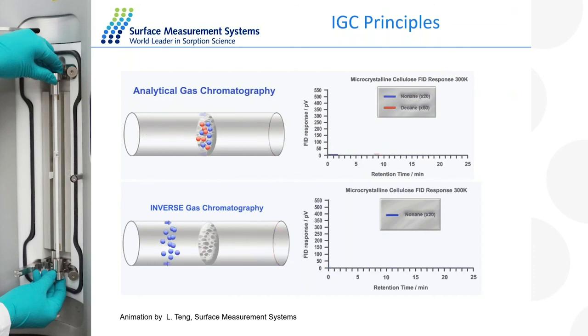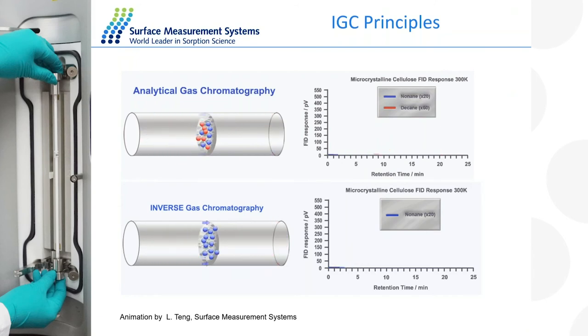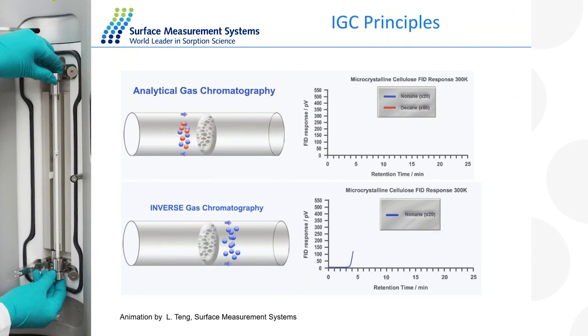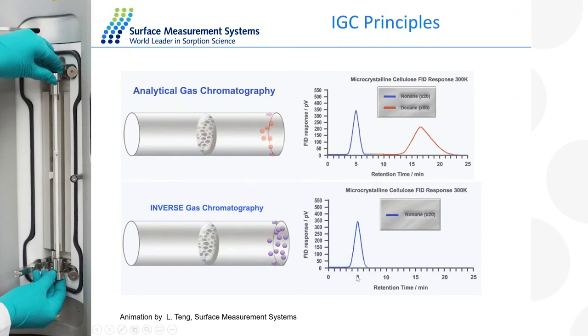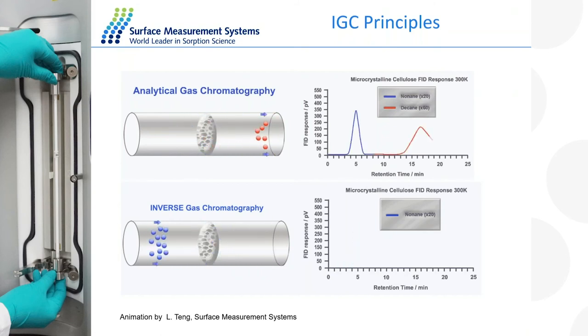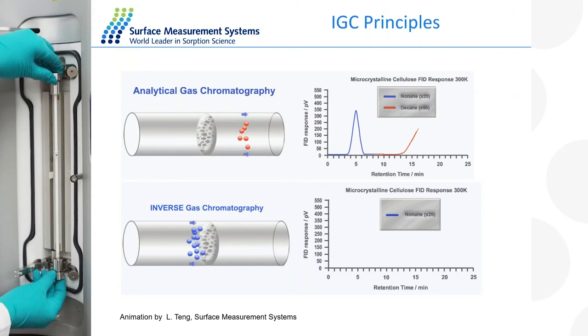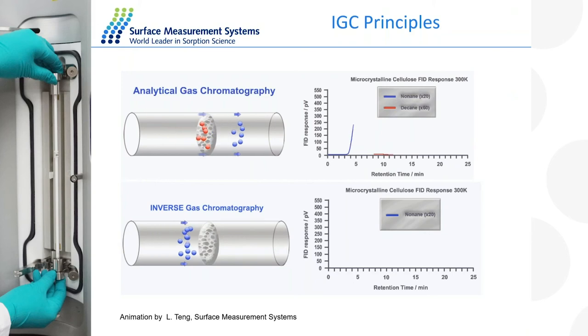In the analytical method you get composition information — how much red molecule, how much blue molecule. In the inverse gas chromatography experiment it's something different. We measure very accurately the retention time, shown in the graph. From the retention time and the flow rate, we measure a fundamental property called the partitioning coefficient — a measure of how strongly the probe molecules interact with the unknown material, the polymer. The example shown is for microcrystalline cellulose, but the model is the same whether it's a polymer or cellulose.